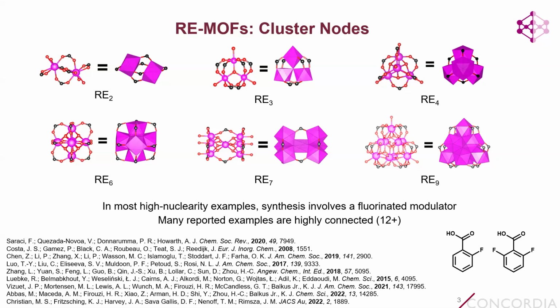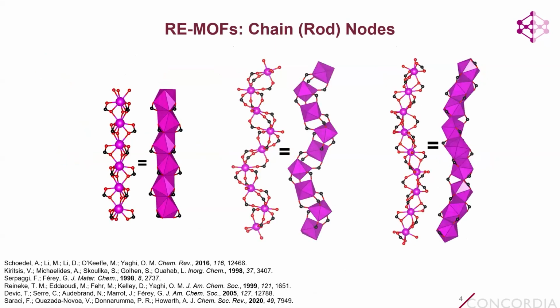Another challenge that arises when we try to make these rare earth cluster-based MOFs is that rare earth elements, when you combine them with carboxylate linkers under solvothermal conditions, have a thermodynamic preference for forming rare earth oxo chains. And so there are quite a few examples of these rare earth chain-based MOFs that have been reported in the literature, but comparatively fewer examples of rare earth cluster-based MOFs. And so I'm going to start today by telling you about some of our cluster-based MOFs and their photocatalytic properties.